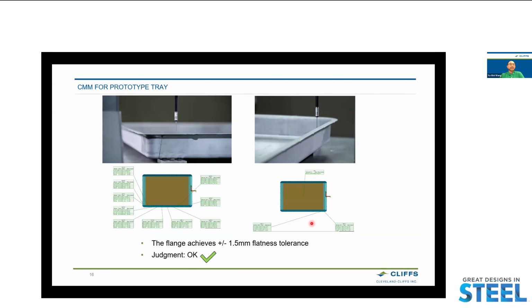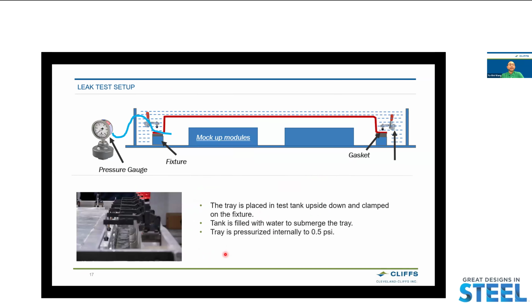And we also conducted flatness measurement, CMM, both the bottom of the tray as well as across the flange of the tray. And we achieved excellent flatness across the flange, plus or minus 1.5 millimeter of the entire flange. So we passed our target. This flatness of the flange is a key to prevent the leak, so for us to meet the leak test target.